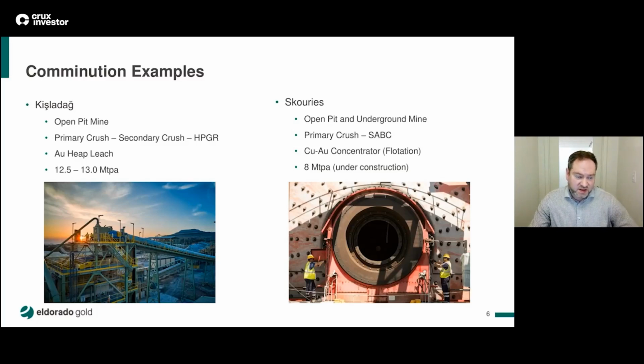We've got Kışladağ on the left side, as I mentioned previously, which is an open pit mine where we have a primary crush, secondary crush, HPGR, and we then recover gold from heap leaching. On the right side is our Skouries project, which is under construction in Greece, where we have a primary crusher followed by an SABC, or SAG mill ball mill, circuit. And this circuit produces a copper gold concentrate via flotation.